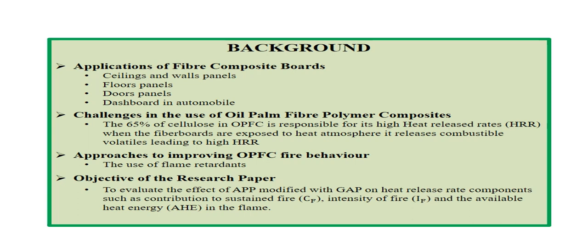doors, dashboard in automobile. However, the challenges of using the oil palm fiber reinforced polymer composites shows that 65% of cellulose contained in oil palm fiber is responsible for its high heat release rate alongside the resin used. When these fiber boards are exposed to heat atmosphere, it releases combustible volatiles, leading to high heat release rates. How can this challenge be tackled?